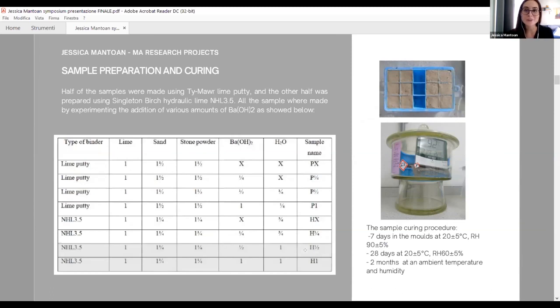The preparation of the mortar was made using 3 different amounts of barium hydroxide: a lower amount, which was about a quarter with respect to the amount of lime; a medium quantity, which was half the amount of lime in barium hydroxide; and an equal amount of barium hydroxide and lime. And I repeated this proportion both for hydraulic and non-hydraulic mortar. Plus, I also prepared a group of samples, hydraulic and non-hydraulic, not presenting any additive, to have control samples with which I can compare all my tests.